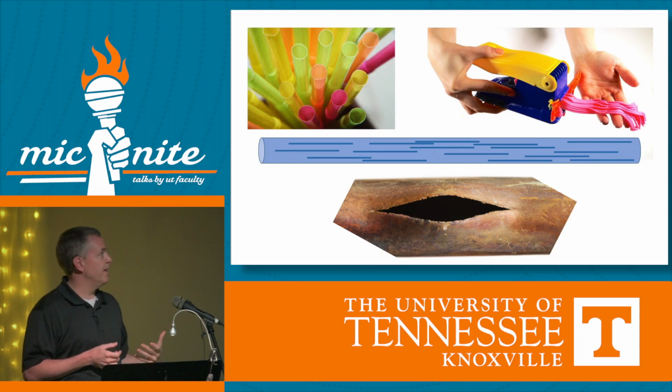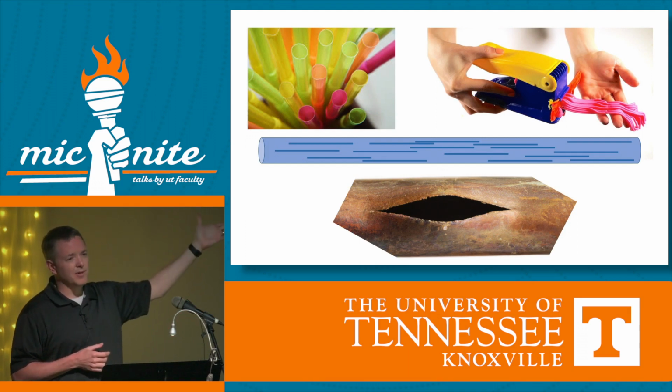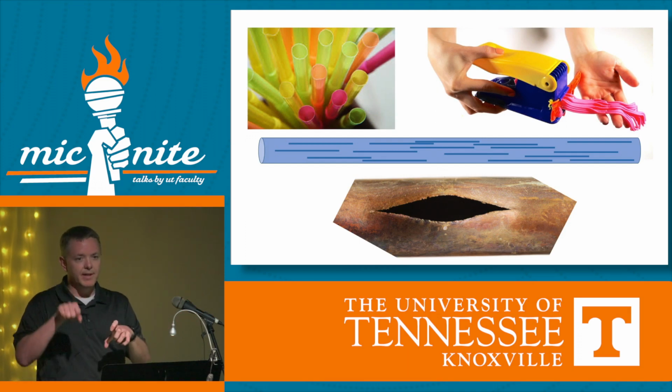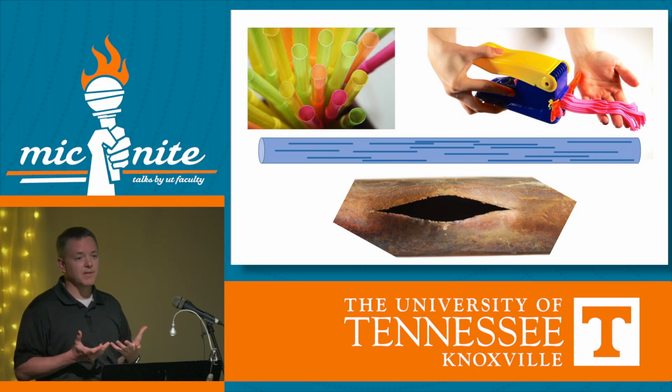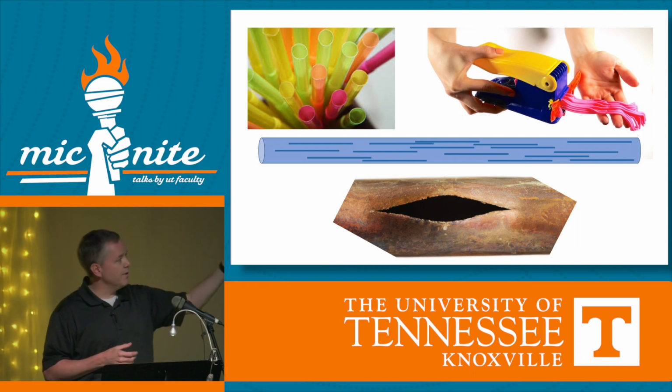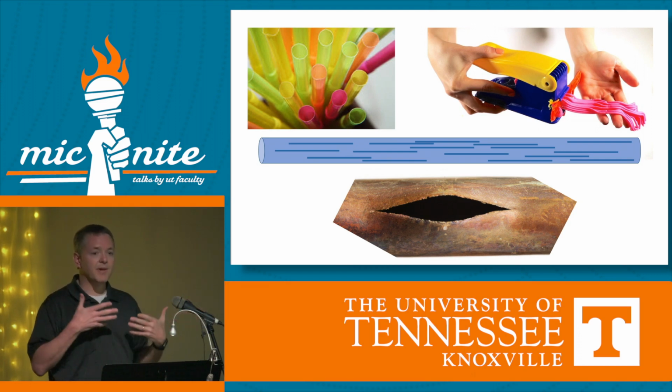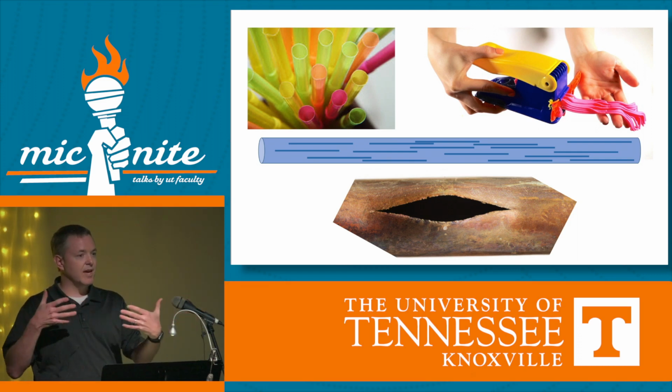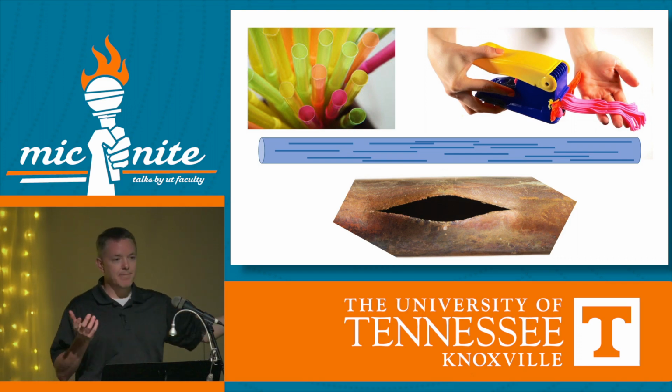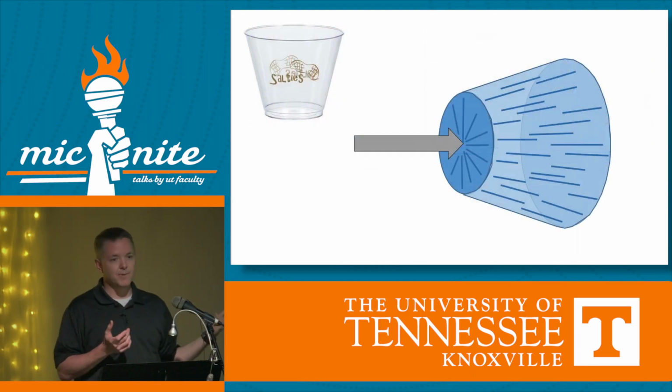natural anisotropy. So if we look at things like soda straws, extruding them, if you ever play with Play-Doh, the extruder, it's the same process. We just do it with hot plastic. All those polymer chains, those spaghetti strands, line up and they create a natural weak section there. So if it busts, if a pipe busts or a soda straw busts, that's where it's going to break.